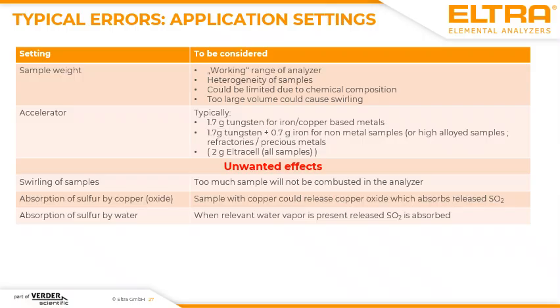One other chance to run your sample is the application of ELTRA, which means you can apply the combination of tungsten and iron as accelerator, which provides the highest energy. And there you can apply typically 2 grams. When you get irritating results with these accelerator and weight combinations, please make sure that you don't have unwanted effects. For example, maybe swirling of the sample, which means that a sample is blown out of the furnace, or that your sample has a large copper content, which produces so much copper oxide, which absorbs SO2, or maybe your sample contains water, which means that the released water absorbs the SO2 and causes minor determination. We will talk about these unwanted effects in detail a little bit later.